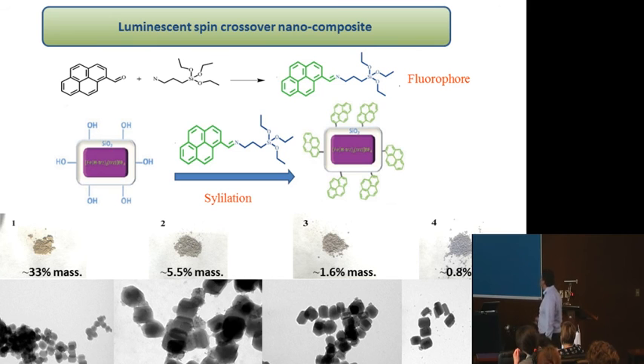In the following step, we wanted to graft different kinds of molecules on the silica shell, in particular a fluorophore. In this case, we use pyrene, which is a well-known fluorophore. This is just a Schiff condensation to obtain these molecules. So you have the pyrene, and you use silylation to graft these molecules on the surface of the shell of the core-shell nanoparticles. You can also play with the concentration of the fluorophore, and each time we obtain more or less the same size of nanoparticles, about 100 nanometers.